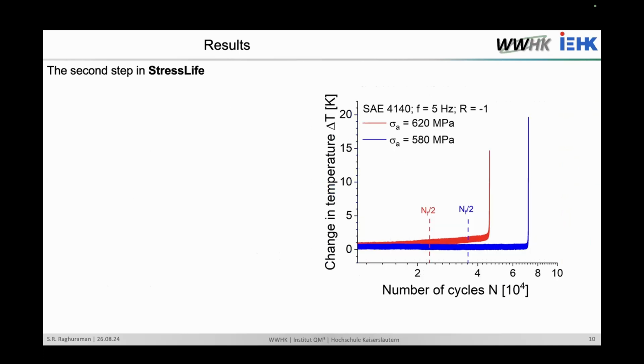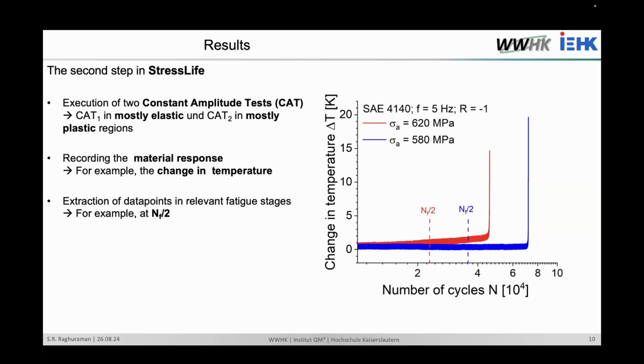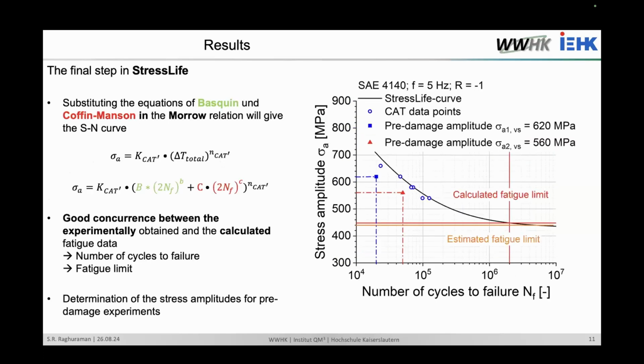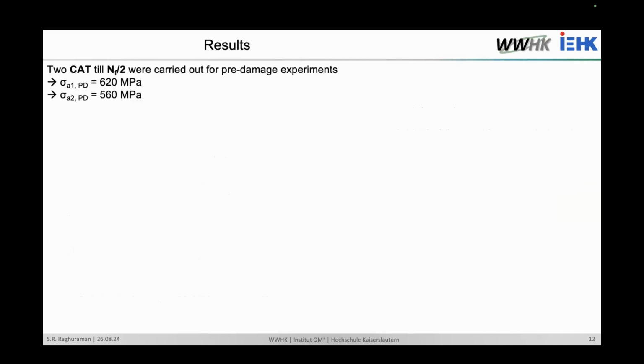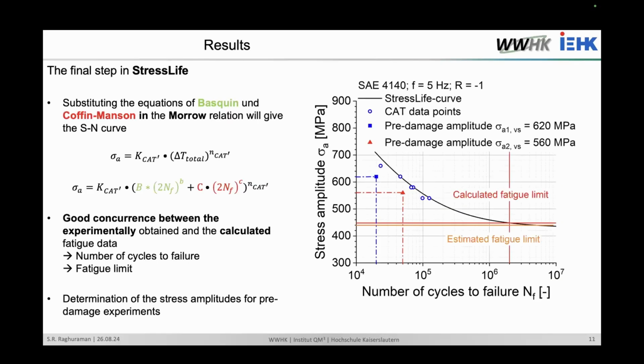The next step will be conducting constant amplitude tests. Here we have conducted two of them, and we have taken the data from the most relevant points, at half of their lifetime, to use again later. This stress life equation is actually a combination of Basquin and Coffin-Manson relations put in the Morrow relation, and thus we get the SN curve here. We can see there is a good agreement between estimated and calculated fatigue limit. For this case, it's around 448 megapascals. And from here, we also have determined our pre-damage amplitudes.